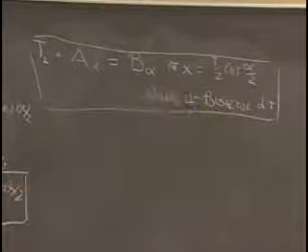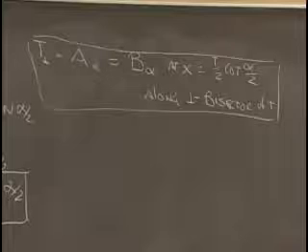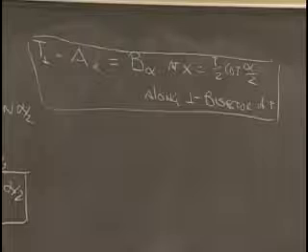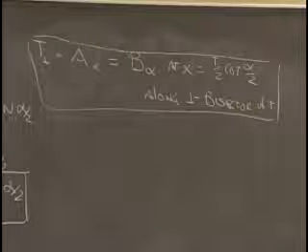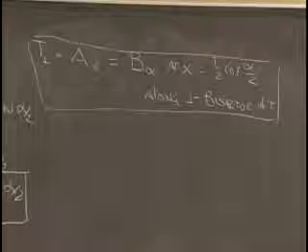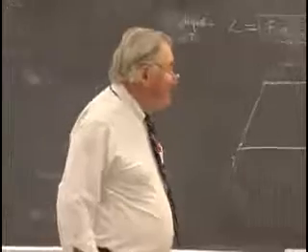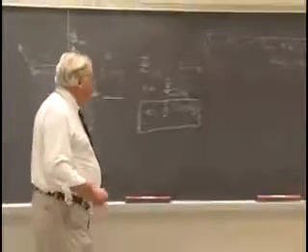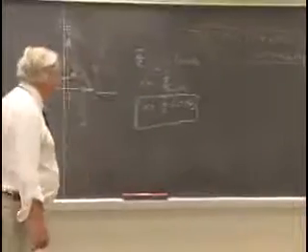So this is a general theorem. This is a fact of two-dimensional life that is always going to be true regardless of alpha. And the only constraint is that the translation has to be added perpendicular to the locus of the rotation axis, and that has to be the case in 2 dimensions because the rotation axis has to always be normal to the space, the two-dimensional space. In 3 dimensions, we'll have to generalize this to make the translation have arbitrary orientation relative to the rotation axis, but we've got enough to chew on at the moment.